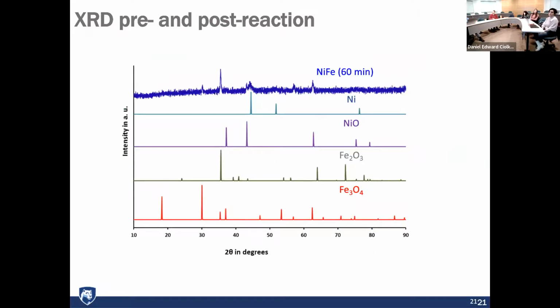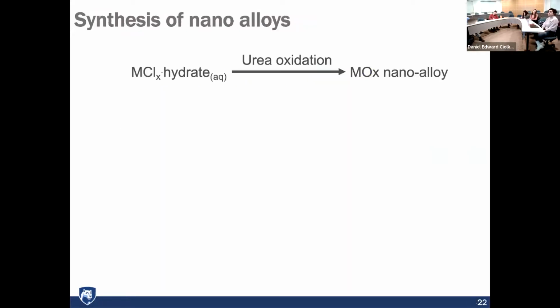But after you do a reaction, you start to see peaks, which again leads us to believe that our catalyst is changing. So this is bad news for catalysts, right? You want to be able to reuse it. If it changes, then you can't reuse it because you're using something different than the first time you tried the reaction. So instead, we moved on to this second generation of materials, which are metal oxide nanoalloys,